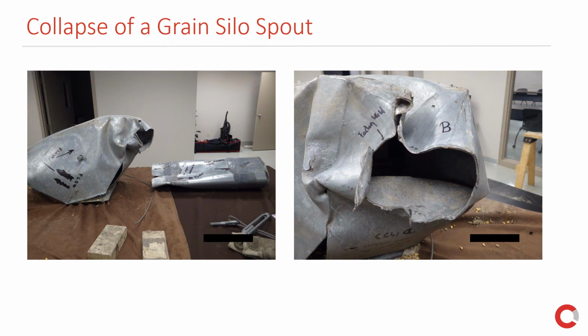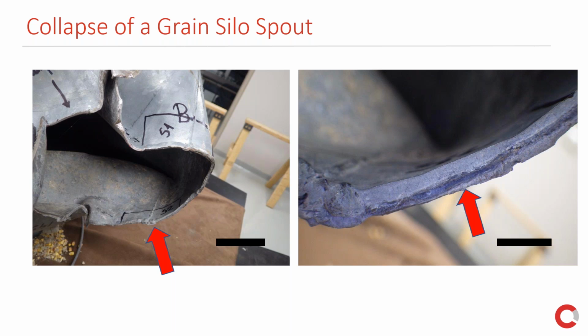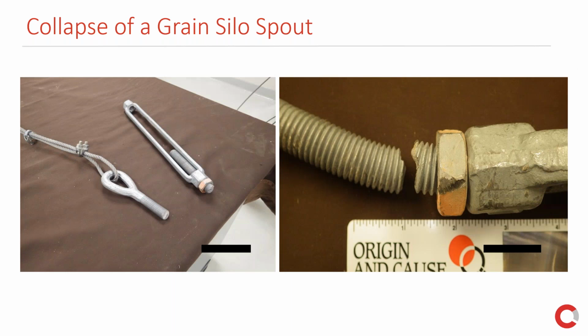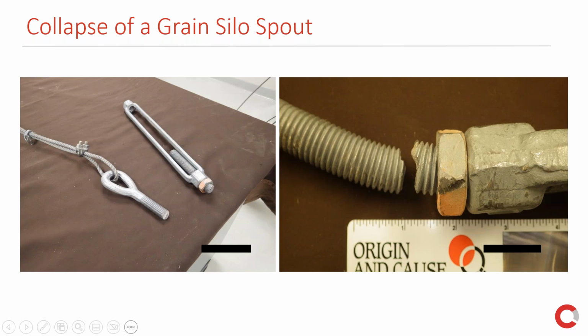This is how the weld of interest was firstly documented, and there are some images showing the weld that looked of interest. Upon further examination, it was found that the weld exhibited several deficiencies, insufficient weld and weld beads, which are not considered good conditions for a weld.